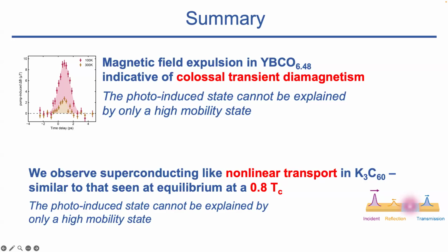So what we have is this light-induced state that clearly has a very large mobility, has a very large diamagnetism, has a critical current. If you had waited another half an hour, I would have told you about measurements of critical currents, which were done in C60. This is kind of superconducting, actually, transiently. This one lives for a nanosecond, this one lives for 5 picoseconds. Is this useful? Probably not. Is this interesting? Very, at least to me.